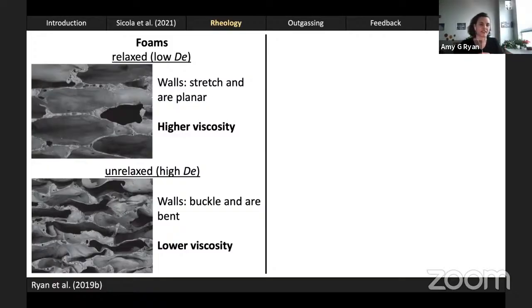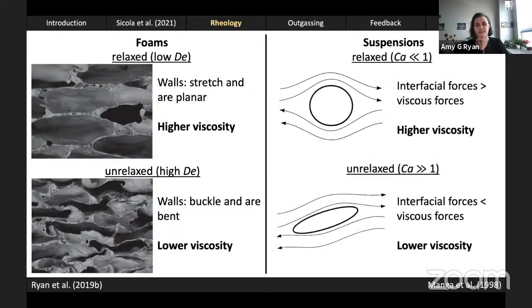Folks in this meeting who think about suspensions may recognize this, may have bells going off in their head, because this is often the way that we think about suspensions, through the lens of the capillary number. If we have a relaxed bubble, one that can maintain its favorite, most stable spherical shape, the melt that tries to flow around it must deflect quite far, as you can see from these flow lines here. And so the overall viscosity of the suspension is quite high.